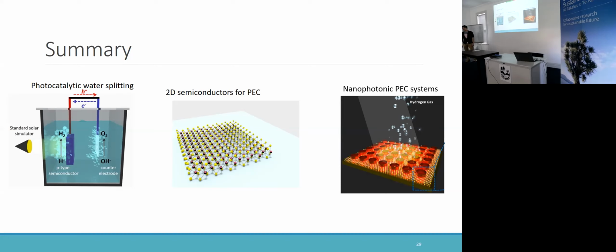So related to that, your laser work clearly showed a thermalization of the energy. Yes. And for the hydrogen reaction, do you see thermalization driving the energy input to the molecules, or do you see more of a traditional absorption? I think it's traditional absorption. At the moment, at least, we don't find any temperature increase in our baths or anything in our experiment. We don't find that.